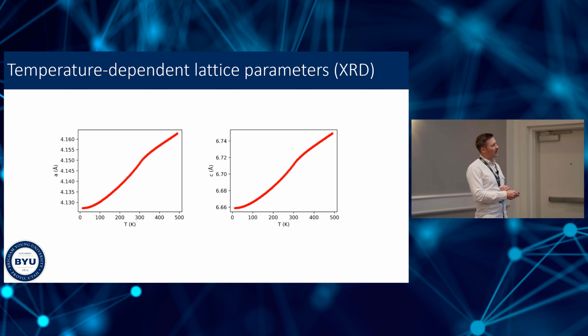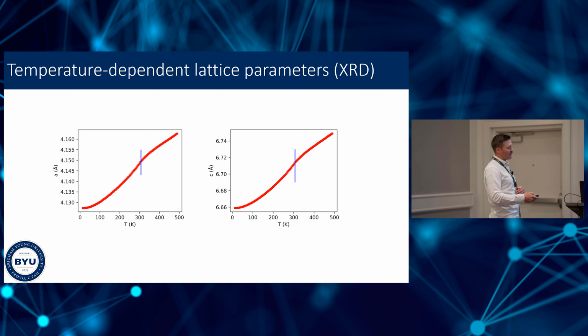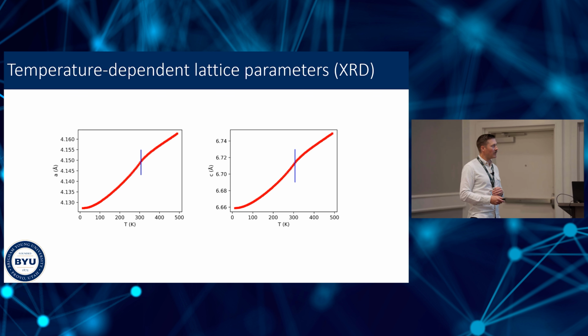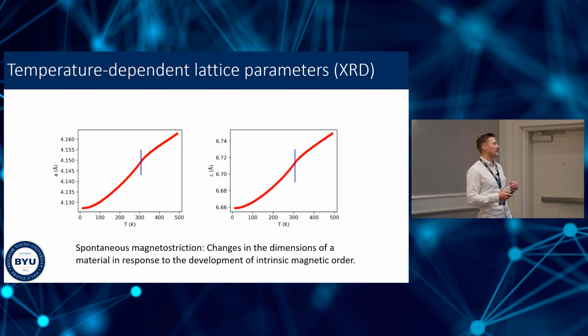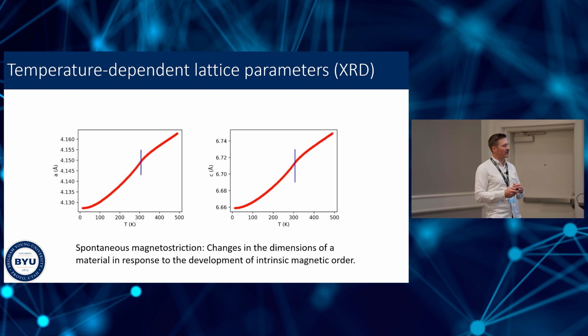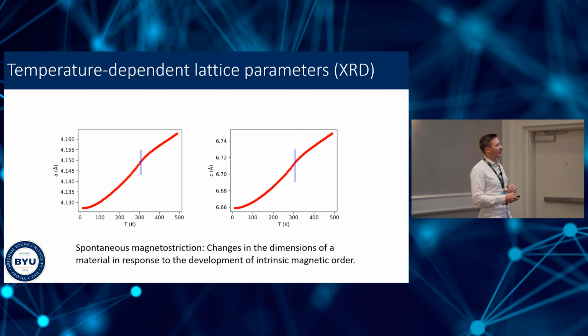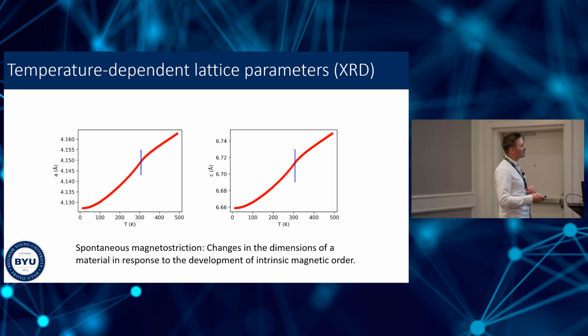Well, I'm showing you here the unit cell lattice parameters determined from X-ray diffraction. And you may notice that there's a kink. We've got the typical thermal expansion here, and then it dips below the high temperature linear trend. Okay, it seems to be anomalously contracting around the magnetic ordering temperature, marked by these blue lines right here. This is called spontaneous magnetostriction, changes in the dimensions of a material in response to the development of intrinsic magnetic order. So manganese telluride is showing this magnetostructural behavior.